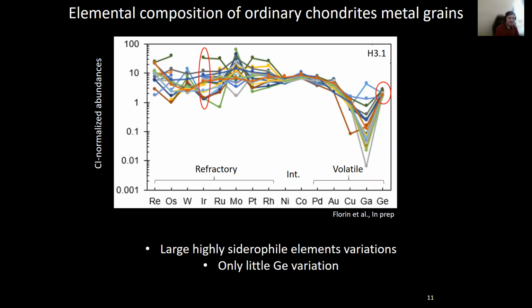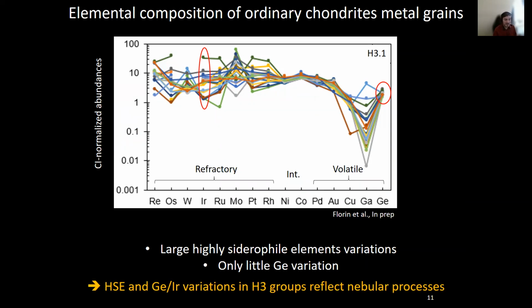So here are our results, and what we can see at first glance is that there is a large variation between each metallic grain, and this suggests that there are many different compositions within the same sample. But if we look at the germanium, it is very well constrained and there is not a lot of variation, whereas for iridium, there is a lot of variation. And because we are studying very pristine objects, these variations reflect nebular processes.